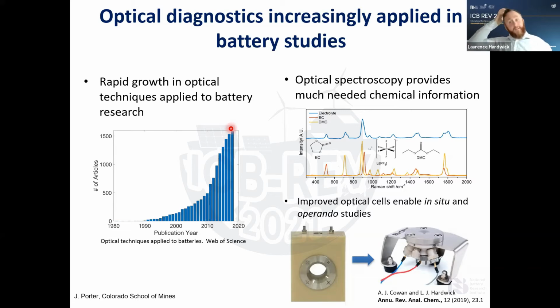Optical spectroscopy provides much needed chemical information on the electrolyte, but also on the electrode and the electrode-electrolyte interface, the interface between the solid and the liquid phase in a liquid cell, and also the solid-solid phase of an all-solid-state battery as well. As you can see here, this is a typical Raman spectrum. We have bands relating to specific functionalities and vibrations, and it can give us information on, say, the coordination of lithium in the electrolyte.